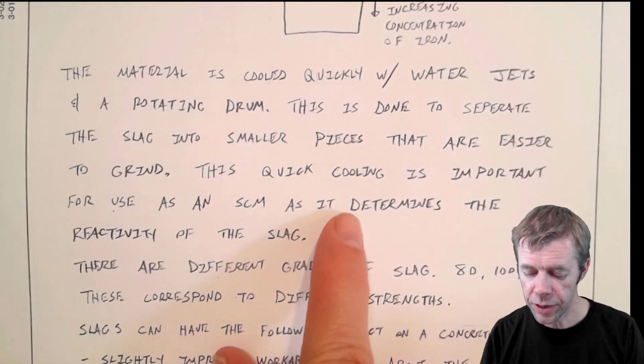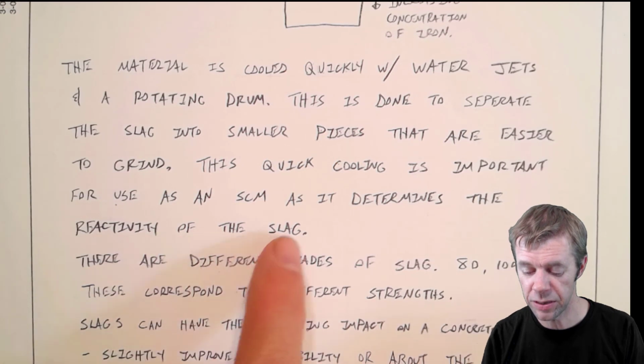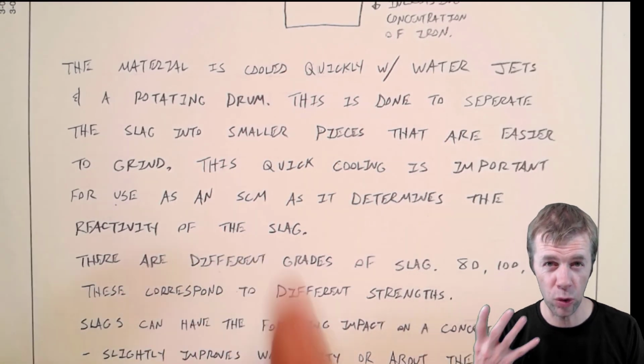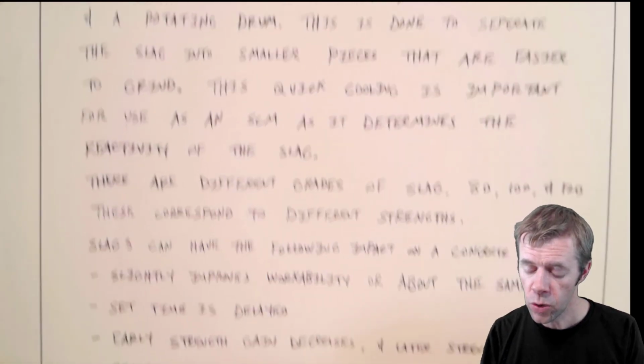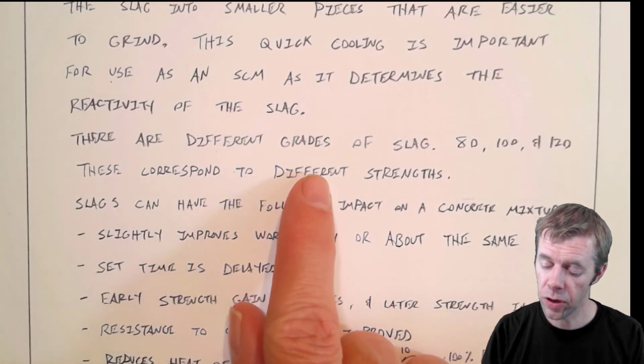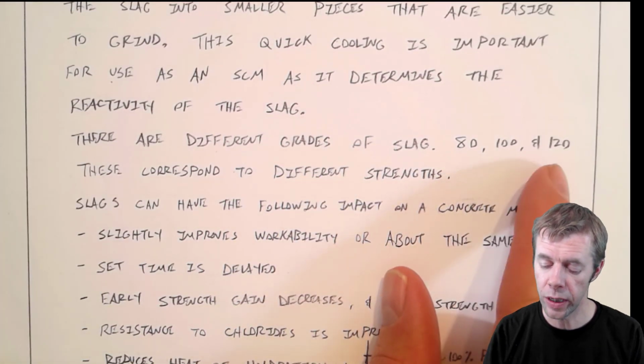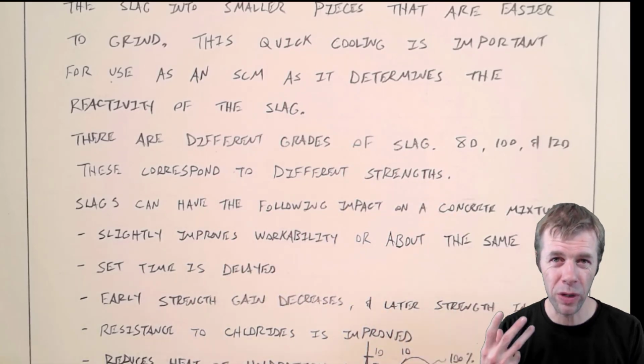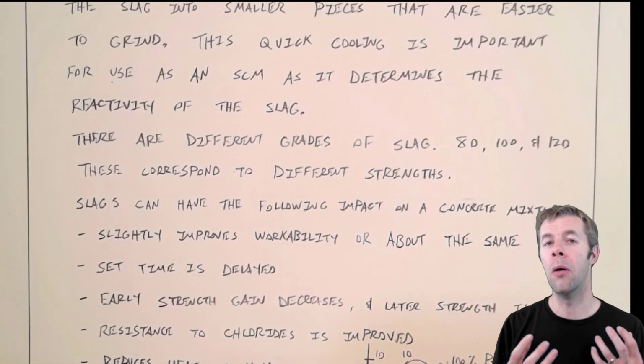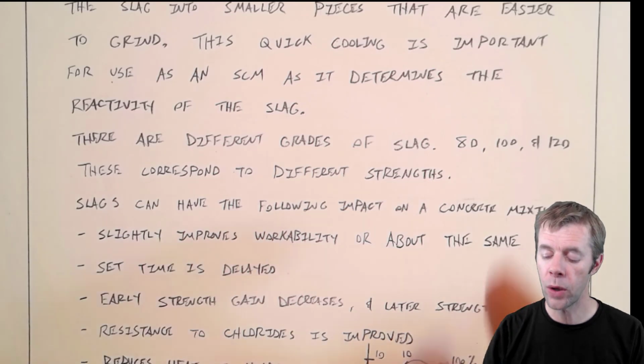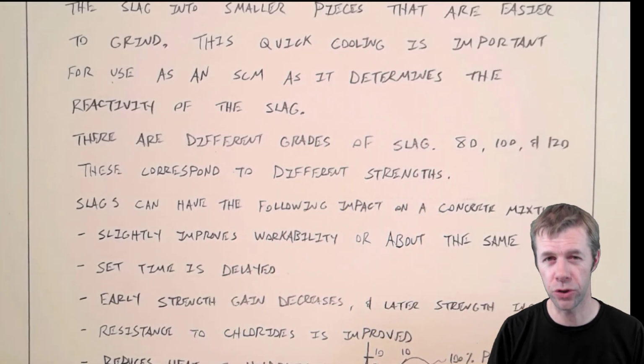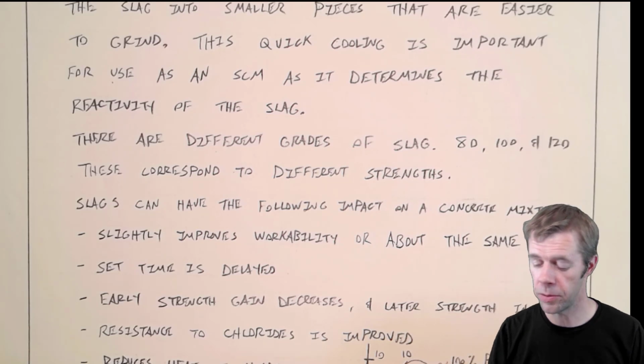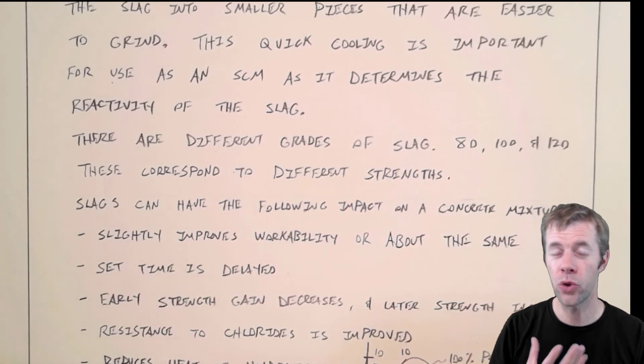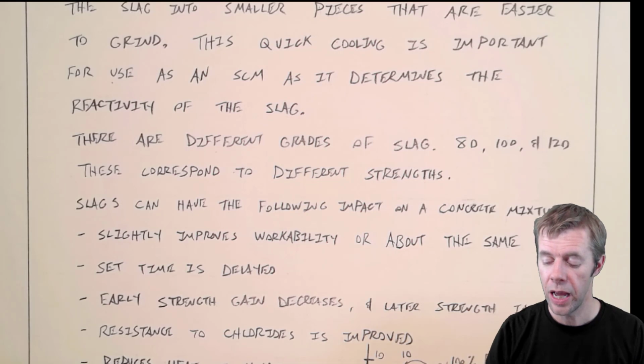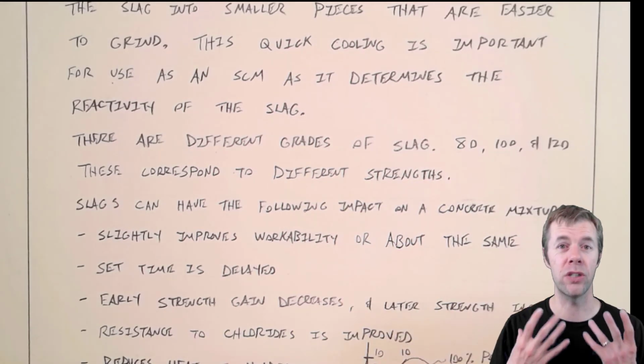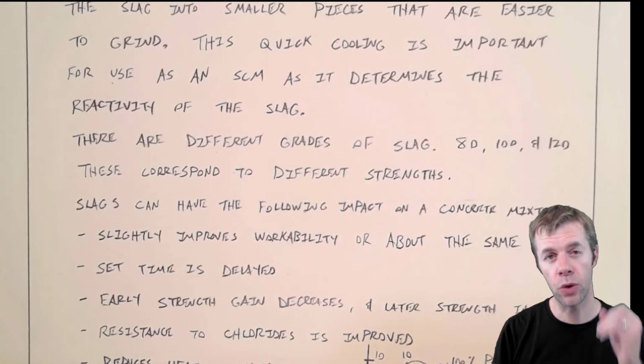And this quick cooling, as I said before, is very important as an SCM because it determines the reactivity of the slag. You want it to be amorphous. So there are different grades of slag: 80, 100, and 120. And these correspond to different strengths, but they really compare with Portland cement. A grade 100 is going to have very similar strength to 100% Portland cement. Grade 80 is going to be about 20% less than Portland cement, and grade 120 is actually going to gain strength faster than a straight Portland cement.